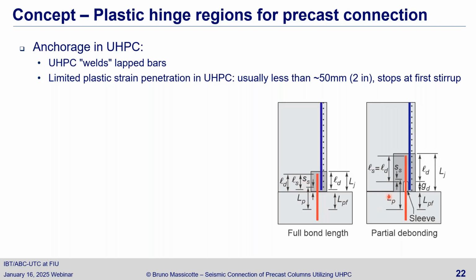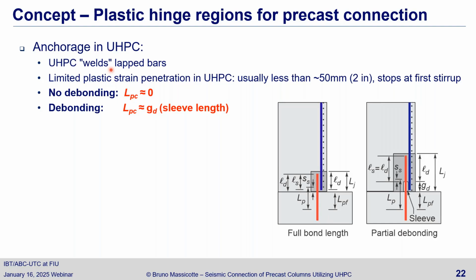But if you want more of the plastic hinge to go up above the footing, into the column, then you can use a sleeve, and you will increase the length of the plastic hinge here. So our experience says that if there's no debonding, when you do your computation, you assume there's no plastic hinge within the UHPC, and if you use a sleeve, then you use that length, and you can select whatever length you want to meet the prescribed displacement.